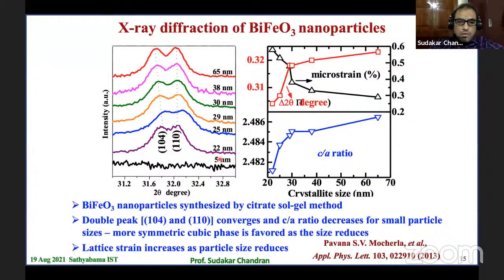For example, the size of the crystals are shown here. As you can see, at very small size, it's more kind of amorphous, but they are crystalline, as I can show you from the TEM picture. As the size increases, you can see that this doublet peak, which is basically one of the 200 peaks in a perfect cubic perovskite structure, splits up. Of course, this split peak in fact moves in opposite direction. Or in other words, if you go down in size, they try to come together, which means the distortion is going away as you decrease the size. And that's what we found.